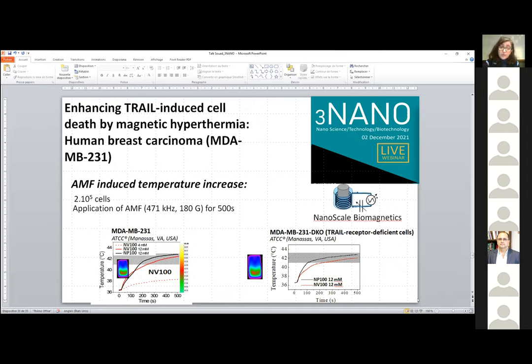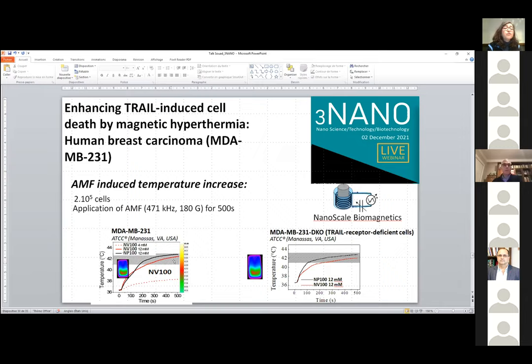Okay, we performed once again the same experiment, but in this case, we introduced human breast carcinoma cells, MDA-MB-231, also provided from the ATCC lab. And we observed the same increase for the same iron concentration. I mean, at 12 millimolar, we have about 41, 43 degrees C along 500 seconds of magnetic field application for both bare particles and our nano hybrids. And we observe the same heating even on TRAIL-receptor deficient cells. That means in this case, we don't have the recognition between TRAIL and its receptor. Okay.